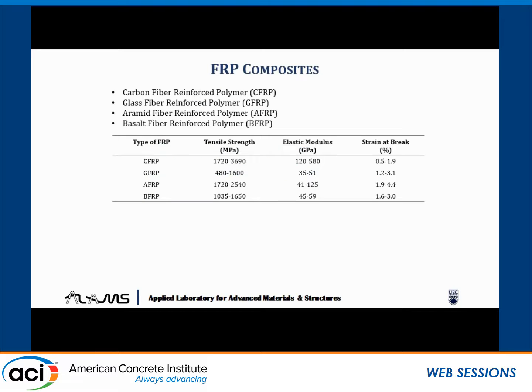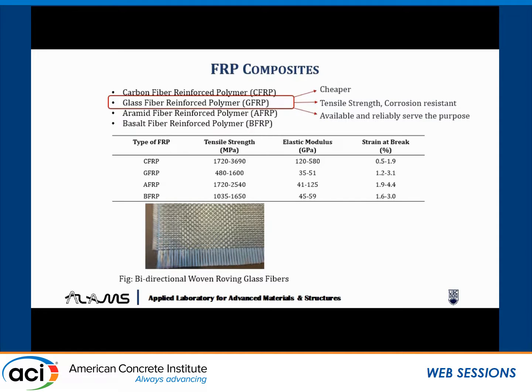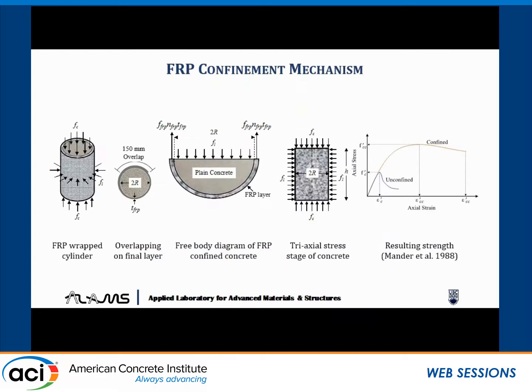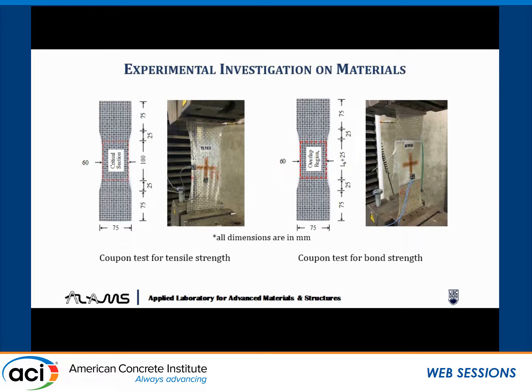That's the intention. This is showing structural grade FRP composites, and we are talking about GFRP. In this particular case, for retrofitting, we use bidirectional woven roving glass fibers, and we use polyester resin and methyl ethyl ketone peroxide as catalyst. What FRP confinement does we obviously know, and our ultimate goal is that it will perform similar to other standard GFRP. But before we proceed, we wanted to see its mechanical strength.